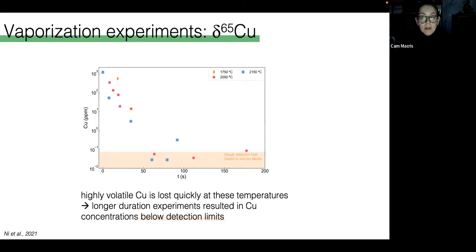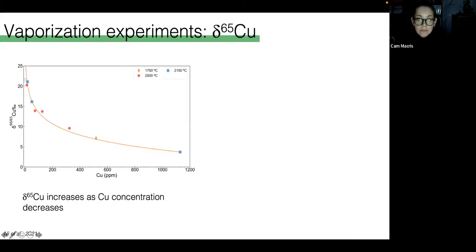We see in this plot of copper concentration versus experimental duration that the highly volatile copper is lost quickly at these temperatures, and that longer duration experiments had copper concentrations actually below detection limits. Here we see that the delta 65 copper of those experimental residues, or the glasses left behind after the heating, increases as the copper concentration decreases, just as we said it should.